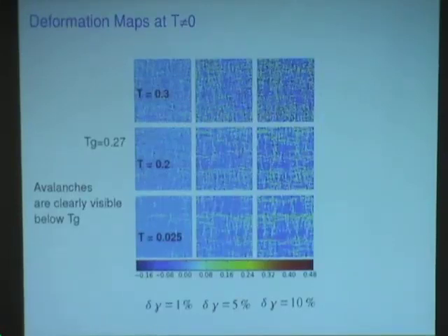And that's at the heart of diffusion. And it does seem to be something missing from these simple potentials or these steady states that's present in the real systems. I know that Michael Falk, in some of his work, has found that localization is very sensitive to aging. And these are somehow always in steady state and rejuvenated.